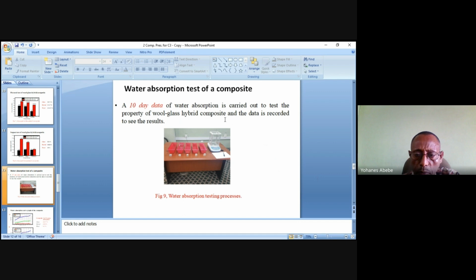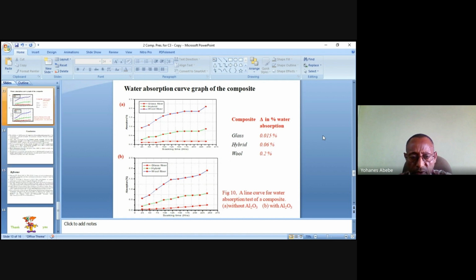When you see the water absorption test of the composite, the 10-day data of water absorption is taken in order to test the water absorption property of the composite. So from the test, a line graph is made from the data. The glass fiber has 0.01% of improvement as a result of nano alumina additions. The wool fiber has 0.2% improvement, and that of the hybrid is 0.6% without the addition of nano alumina in this case.